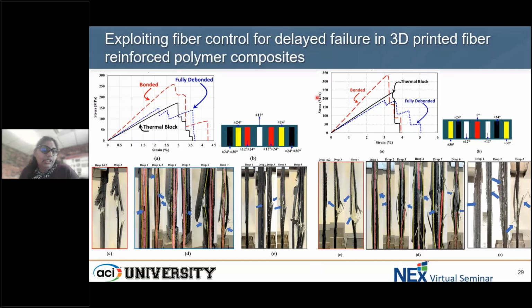For the fully bonded configuration in design 2, which is the red line here, attributed to the red box here, there is failure in 2 to 3 stages. In the blue box, fully debonded, many drops were seen, with damage in different layers, not all together at once. Drop 7 finally showed the complete damage.